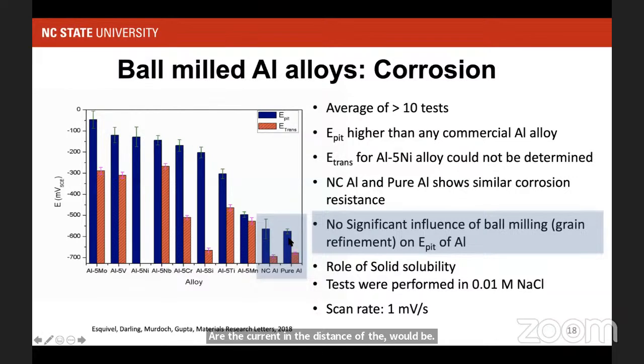So if I take the pure aluminum here, this is pure aluminum on the far right corner, right? In the beginning, if you remember, we talked that pure aluminum is the most corrosion resistant among this aluminum series of alloys, right? So that's why we're taking that as a benchmark, the most corrosion resistant one. If I compare the pitting potential of that with aluminum vanadium, for example, you see a huge increase in the pitting potential, a huge increase in the transition potential. What that basically indicates is that these materials, the ball mill materials, have really high corrosion resistance, right?